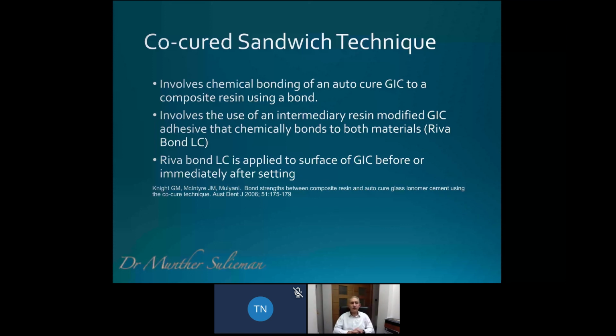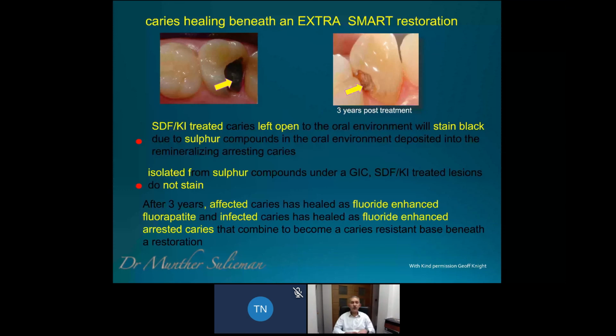Okay, just the final few slides. Again, this shows you now Riva Star. If you just leave the cavity open, it will pick up sulfur compounds from the oral environment, and also will stain. Just in the same way as arrested caries in the mouth will actually absorb the chromogens from the environment and stain, whereas with the use of potassium iodide and with the use of putting a glass ionomer filling on top, you will actually not get any staining. As you can see here, after 3 years, they've removed that and there's hardly any staining going on.